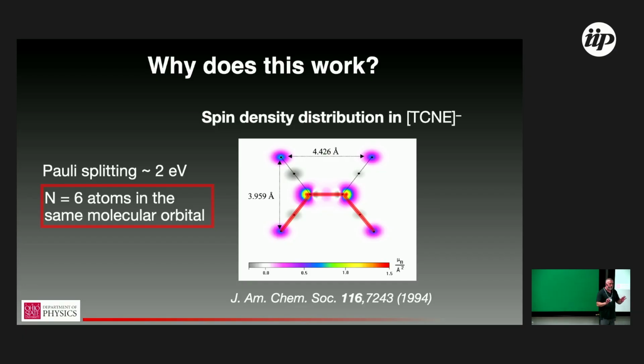If we're thinking of a traditional solid state material, that feels like a long distance because you're hopping from atom to atom to atom. The fact that the TCNE is retaining some of its molecular character means that there is a delocalized molecular orbital that extends over the entire small molecule. So it's really more a next nearest neighbor type interaction, that we can really think of this molecule as an artificial atom, right? Which is a phrase that the quantum dot community coined, but I think translates reasonably well into this picture. So this is my first explanation of why we can have such strong exchange coupling leading to high temperature magnetic ordering in a material where the spins are so far apart.